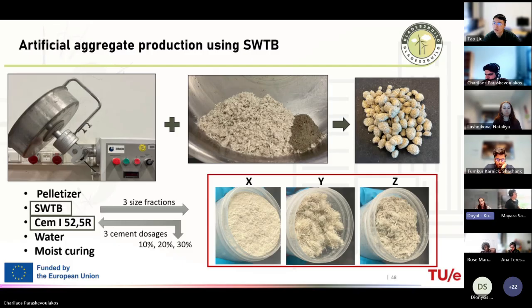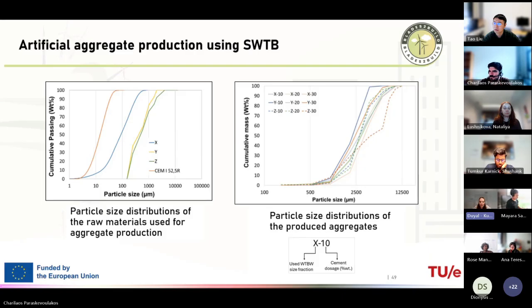The problem of pelletization is that it is usually a method to create pellets, or so-called artificial aggregates, from hydrophilic materials. However, since this waste material is quite hydrophobic, we needed to develop an engineered pelletization process to have strong aggregates.